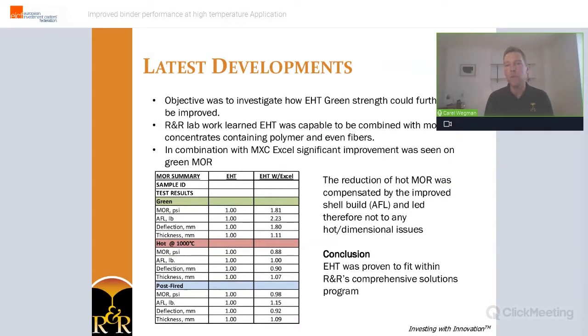Although the focus of EHT will always be on hot strength performance, it is what it is designed for. We wondered at R&R how its performance would be influenced when it is combined with a modern binder concentrate, whereas EHT itself holds no polymer. The concentrates in what we call our Matrix Coat family of products contain polymers, surfactants like antifoam, wetting agents, bactericides, and in some cases, even fibers. We combined EHT with our MXC Excel concentrate with the main objective to improve the green strength.